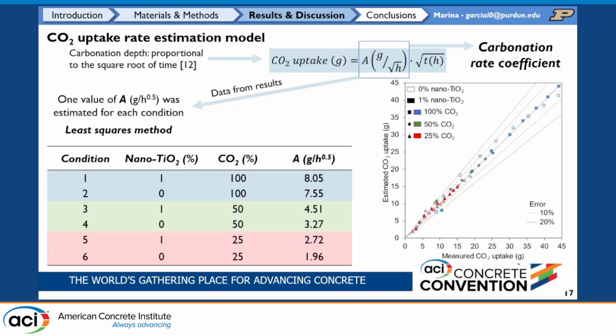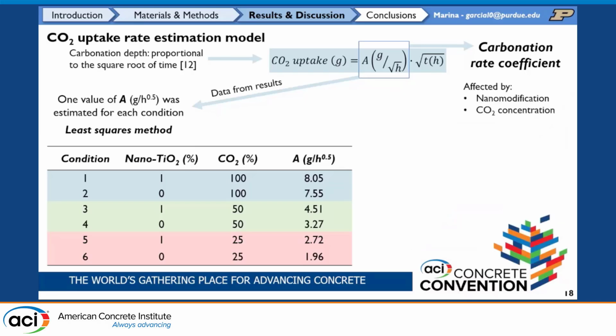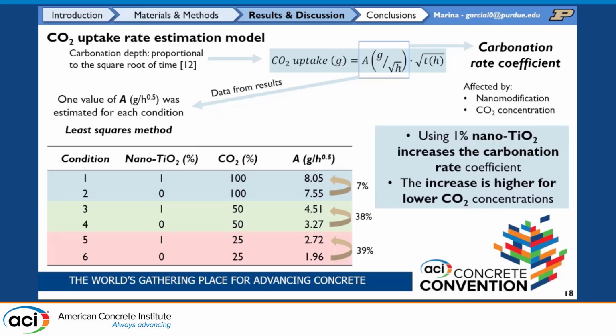These are the estimations that we got, and as you can see, on the y-axis, the estimated CO2 uptake with this formula that I'm showing right here, and on the x-axis, the actual measured CO2 uptake, we're getting a pretty good estimation. And also, as you can see, adding those nanoparticles has a much bigger effect on the samples that were exposed to lower CO2 concentration. And that might be due to the fact that at 100% CO2, having high levels of CO2 in the air is already accelerating this reaction a lot. So the effect of titanium dioxide nanoparticles is not as significant. Whereas if you lower the CO2 concentration, this effect is enhanced. As you can see, we're getting almost 40% of increase in the CO2 uptake rate. So we're accelerating this reaction around 40%.